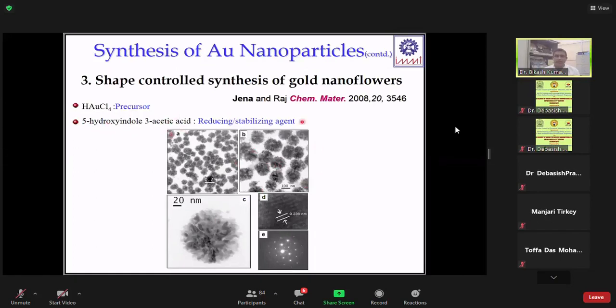That one is very simple. Within 20 minutes of stirring, you take the precursor and add this reagent. This is a biomolecule. You put it in and stir for a while, around 10 to 20 minutes, and then you can see very nice marigold shaped nanoparticles form. So what I'm going to show is how this green way of synthesis is helping to develop different shapes of nanoparticles. We have observed some other applications, not biomedical, that's why I'm not showing the applications here. But it has very interesting applications when compared to the spherical counterpart.